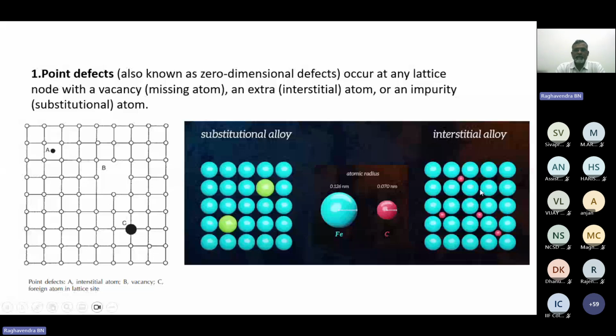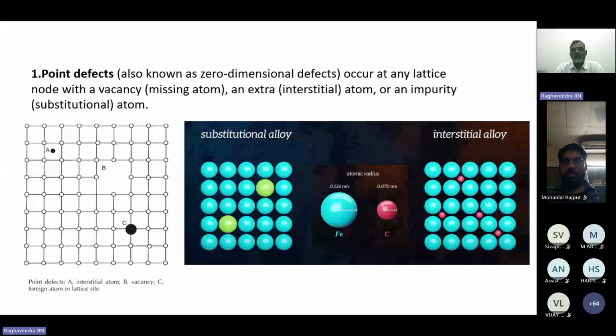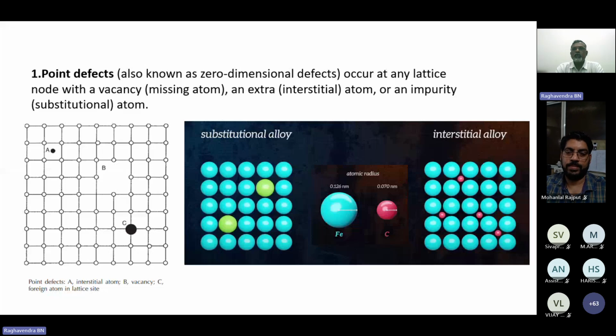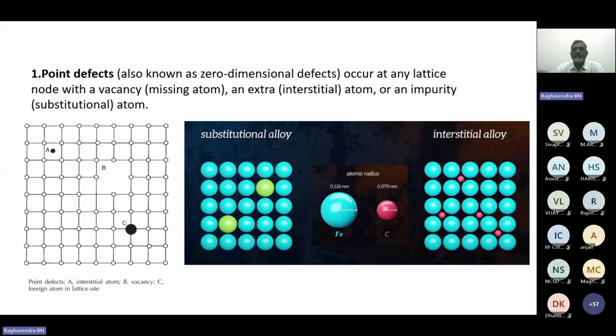Substitutional alloy means the same size or slightly bigger size will replace an atom. So we call it a substitutional alloy. Here we need to understand one thing: even though it is a point defect, we are going to use this defect for changing the mechanical properties of steel or cast iron, casting. How can we change? For example, you all know heat treatment. We do case carburizing. When we do case carburizing, the carbon atoms go inside through a diffusion process, and sit in the voids present in the face centered cubic structure. So this point defect, we are using it for changing the mechanical properties.